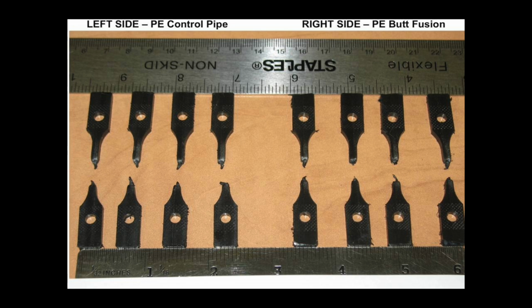These are the actual tensile impact specimens after testing, and these are the butt fusion on the right. You can see in every single case elongation, ductile tearing, typically just one side or the other of the butt fusion. This is an indication of a properly made butt fusion when you see this ductile elongation.